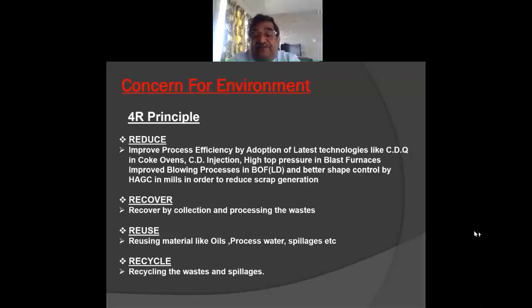So in all plants, we strive very hard to reduce the carbon emission. And a steel plant is an organization which consumes coal very heavily, because coal is required as coke for melting the iron ore and getting iron. Another area of concern in the plant is another resource which is extensively used: water. To give an idea, even the makeup water, which constitutes around 3 to 4%, is like 5,000 meter cube per hour. So water is another resource which has to be handled very carefully, and most of the water is recycled.